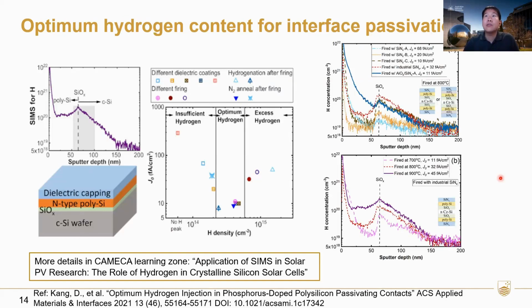I'll go through some examples here. The first one is work from my colleague Di Kang, studying the effect of hydrogen content at the interface of the polysilicon. If you look at this SIMS image here, the silicon oxide interface is roughly around 70 nanometers, and the concentration of hydrogen in this region is integrated and plotted as the x-axis, and compared with the J0, a measure of the surface recombination.